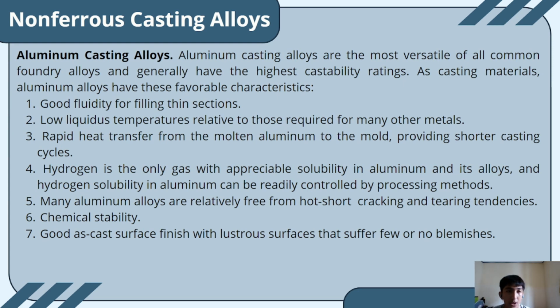The first is good fluidity for filling thin sections. Second is low melting temperature relative to that required for many other metals. Three is rapid heat transfer from the molten aluminum to the mold, providing shorter casting cycles. Four is that hydrogen is the only gas with appreciable solubility in aluminum and its alloys, and hydrogen solubility in aluminum can be readily controlled by processing methods. Five is that many aluminum alloys are relatively free from hot short tearing and cracking tendencies. Six is chemical stability. And seven is good as-cast surface finish with a lustrous surface that has few or no blemishes.